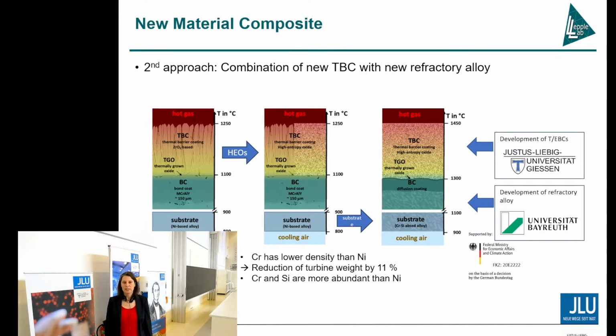The second approach is that we combine the new TBC materials with new refractory alloys, and this is what we are doing in a joint project with the University of Bayreuth. So there we are now introducing, instead of the nickel-based superalloy, a chromium-based alloy as the substrate material. And the advantage is that chromium has a lower density than nickel, and thereby we can reduce the weight of the turbine by 11%, which also reduces the use of fossil fuels. And also chromium and silicon, which is also used in this alloy, are more abundant than nickel.